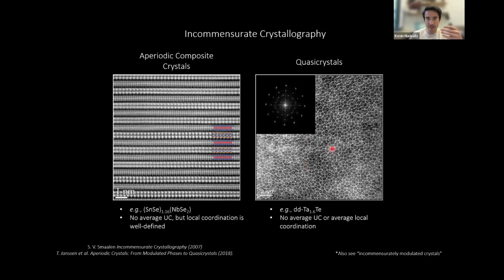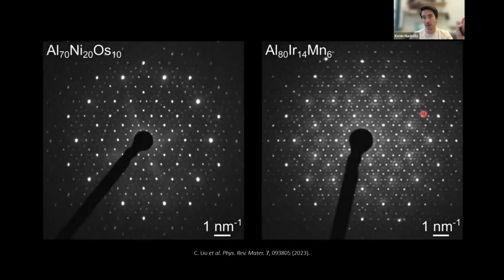So when people started discovering these, they had many examples, and they became very perplexed because although if you look very carefully, up close at the lattices of these incommensurate lattices, they look disordered. But if you do diffraction on these crystals, you find diffraction is beautiful. Diffraction has a dense array of sharp diffraction peaks, where the sharpness of these diffraction peaks is often comparable to what you'd expect of a purely periodic lattice. This makes no sense if you take it at face level.